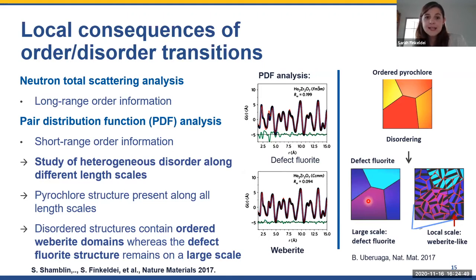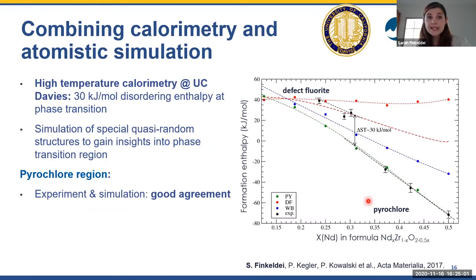And after these findings, which we published in Nature Materials a few years ago, we were interested in understanding more about this order-disorder transition with the new knowledge that we had just obtained. So we performed a combined calorimetric and atomistic simulation experiment, and that was done together with Professor Alexandra Navrotsky when she was still at UC Davis before she moved to ASU. We performed high temperature calorimetry measurements at UC Davis, and you can see the formation enthalpy here dependent on the chemical composition of a pyrochlore. So you can see an increase in neodymium content.